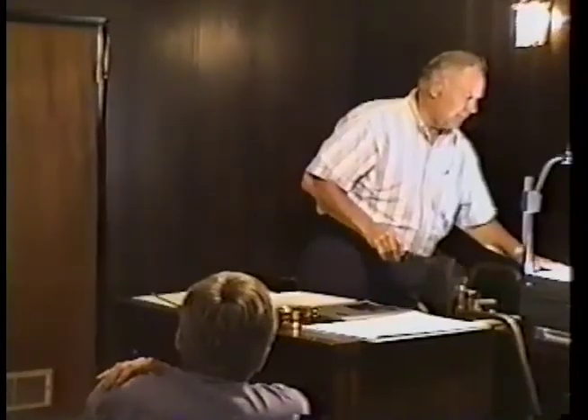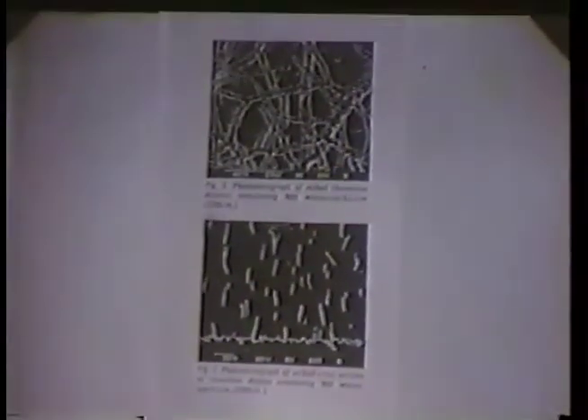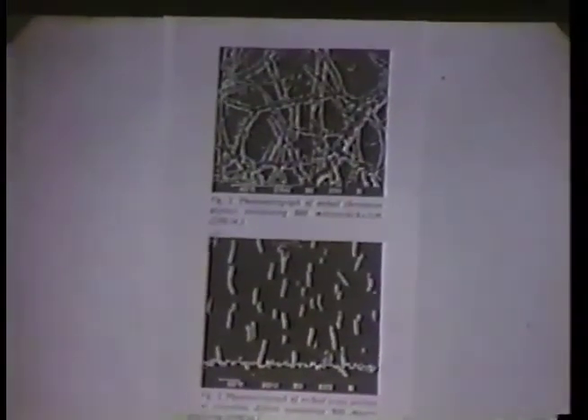Does controlling this part of the process control your porosity too? It's contributed to the final porosity, yes. More so with other people's processes than with ours, but yes. More porous chrome means that there are actually more of those cracks in the chrome. I'll get into what's called the reverse current etch process. This is a cross-section of that microcracking phenomenon.